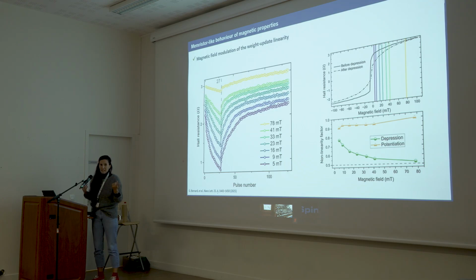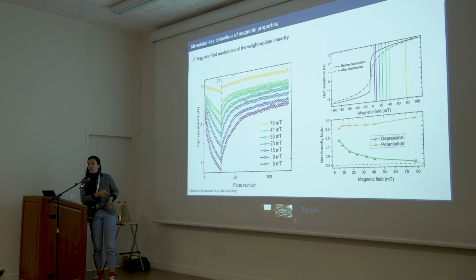So if the magnetic field is pointing up, we have a competition between the effects of the gate, wanting the spins to go in plane, and the magnetic field pushing them out. In an intermediate competition between these two components, we can find these interesting effects that we see here. So it's really a competition between the effects on magnetic anisotropy and the strength of the magnetic field.